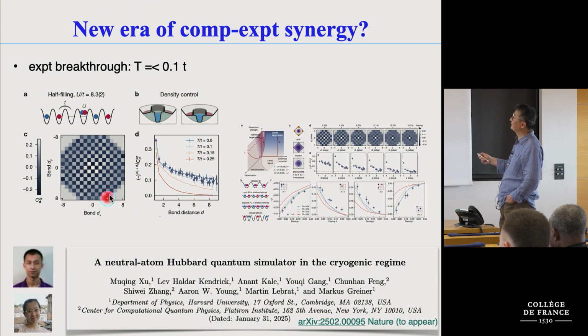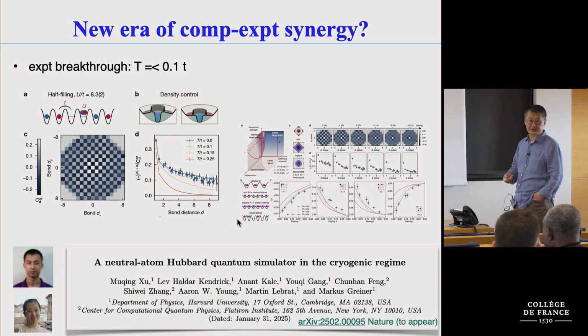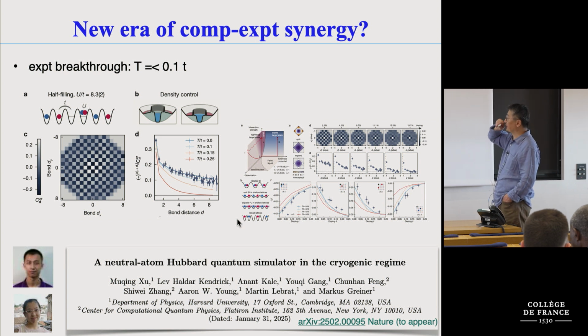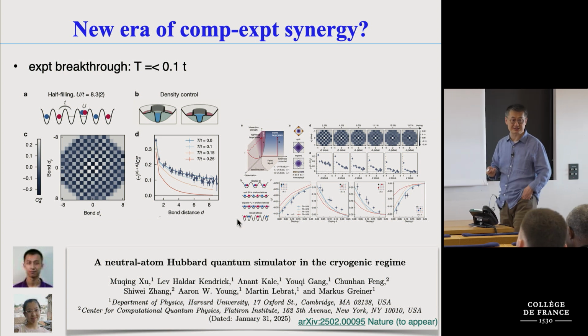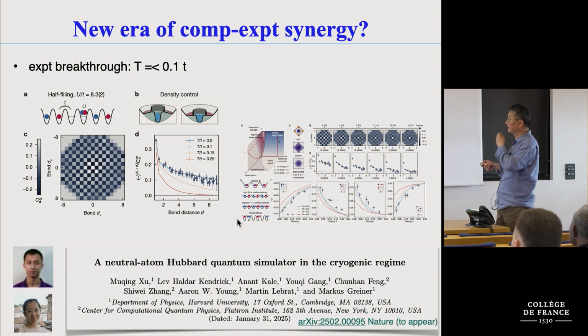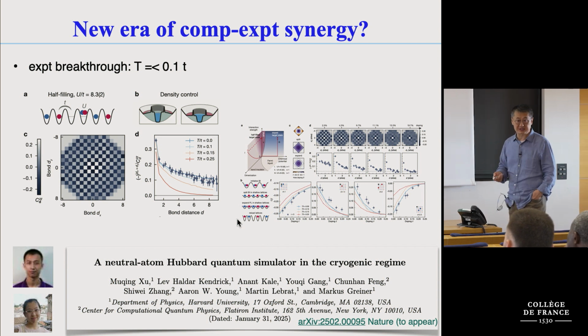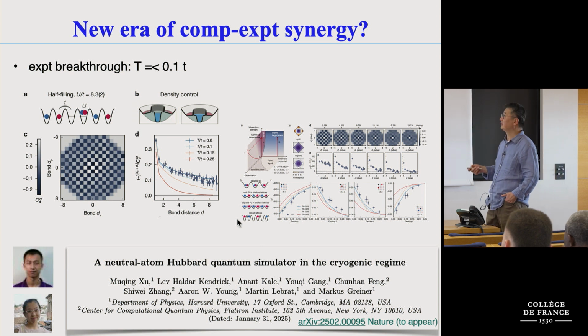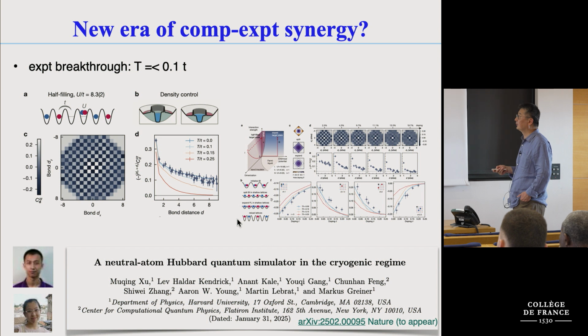And then this is half-filling, the left. The right is doped cases with different doping, but short-range correlations, where we've done the calculation, which are these lines for different temperature. And then these are different correlators, indicated here: 1,0, and 1,1, and 2,0, and so on. You can see that the temperature is consistent with being lower than the lowest temperature we compute, or sometimes even lower than our ground state, but I think that's small systematics in the experiment. So this is very exciting because now there's an opportunity to really look at the more challenging physics in the Hubbard model.